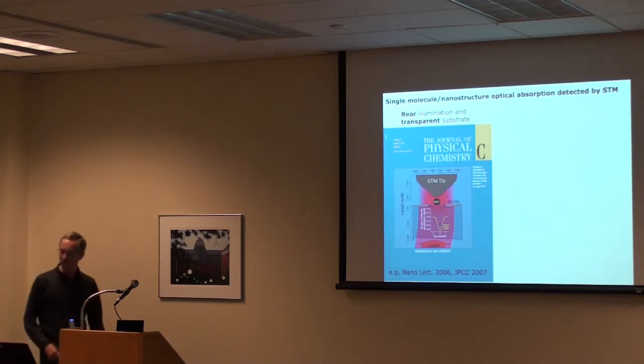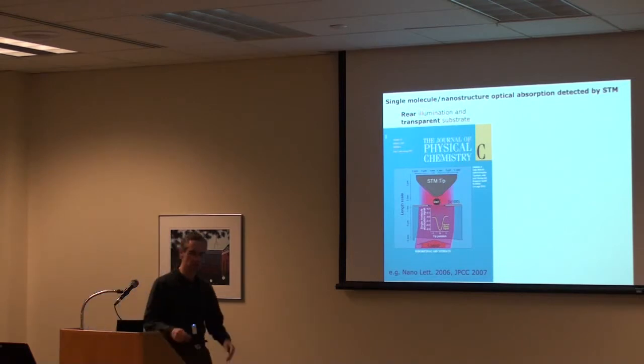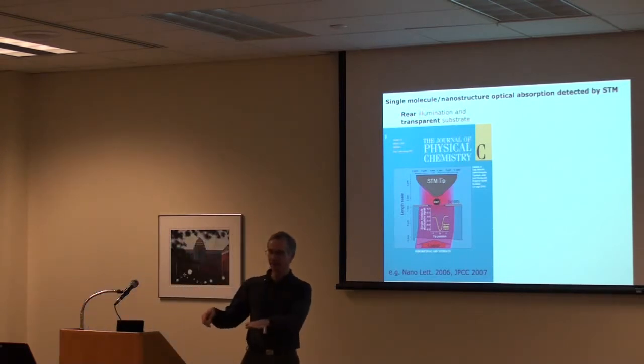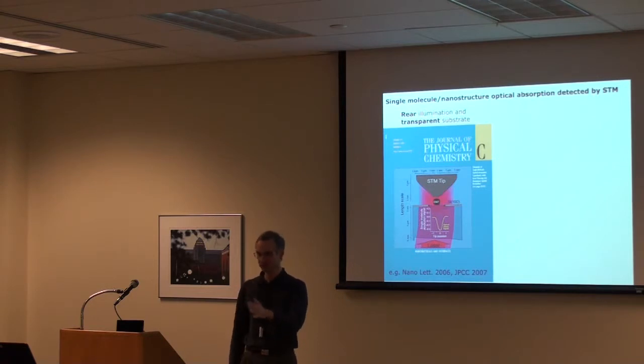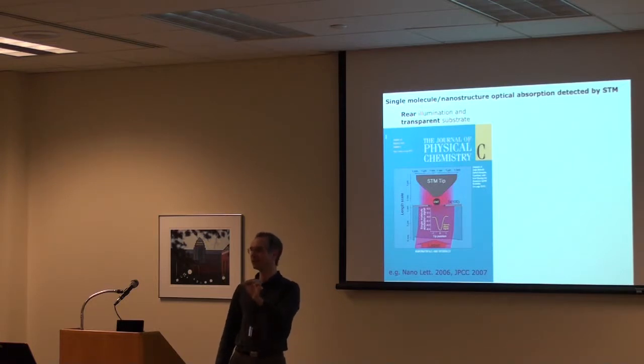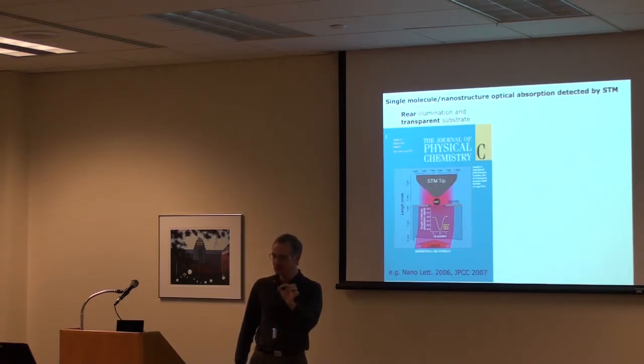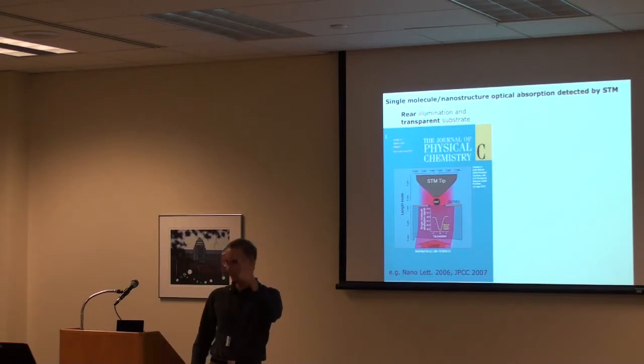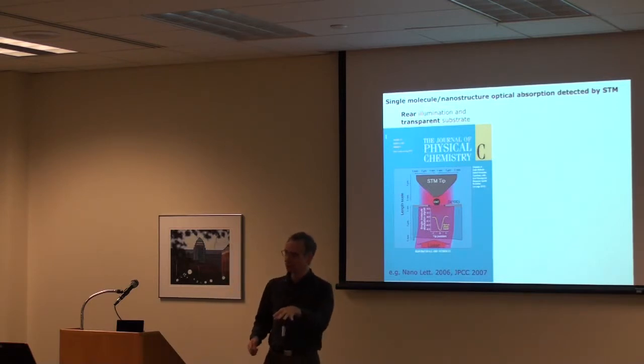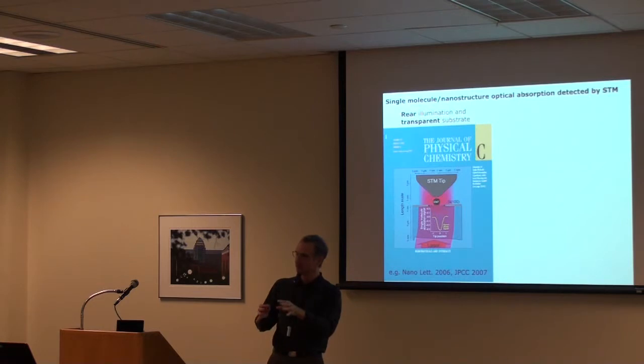There's one other trick that I'll briefly mention, which is that you can't just scan over the surface with the laser off and look at the molecule, and then scan over the surface again with the laser on and look at the molecule. The reason is, for any people here who do STM, it would be impossible to scale and register the two images to see those small sub-angstrom or angstrom variations between the absorbed and the non-absorbed molecule. So we have to come up with a technique where we can subtract the signals directly as the scanning is being done.